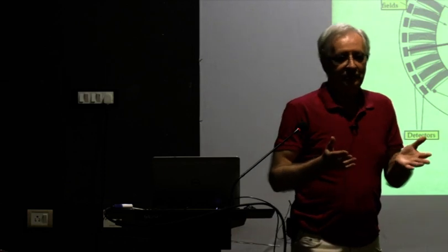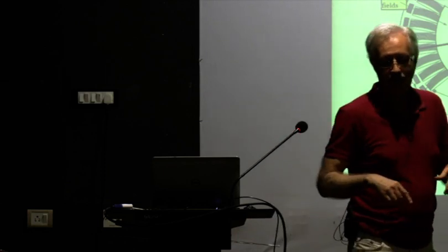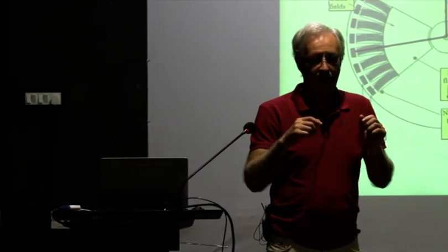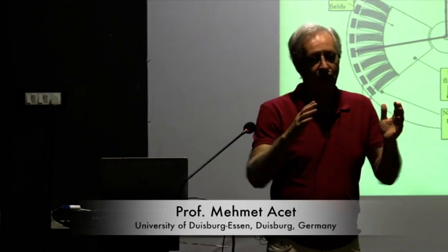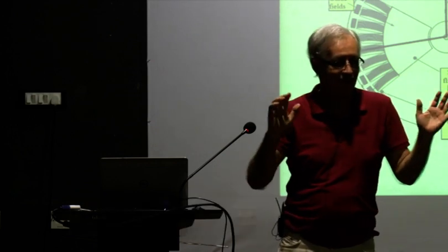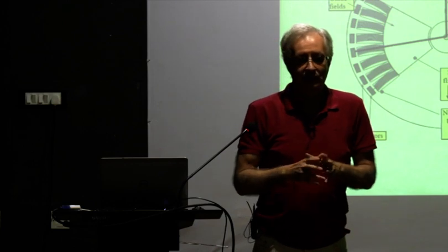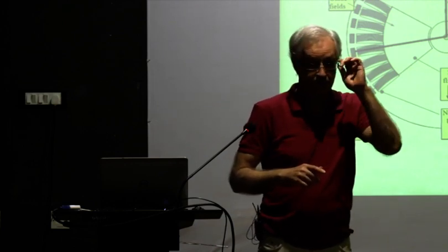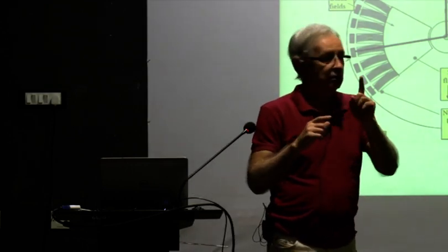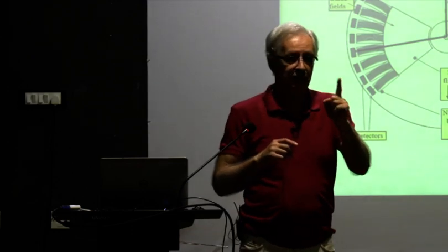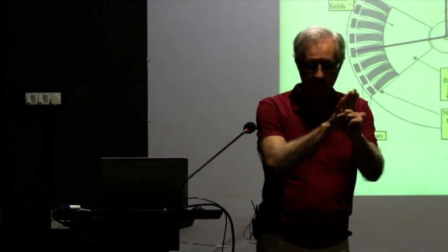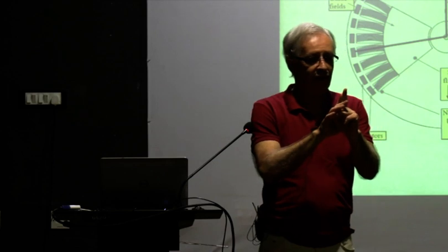Bragg peaks can be broad, Bragg peaks can be narrow. And in fact, in the case of magnetism, they can get so broad and broad and broad that eventually you have something diffuse, centered about a certain peak. So, if we have a very well-defined sharp peak at half Q, that means we have a well-defined antiferromagnet in the magnetic structure.